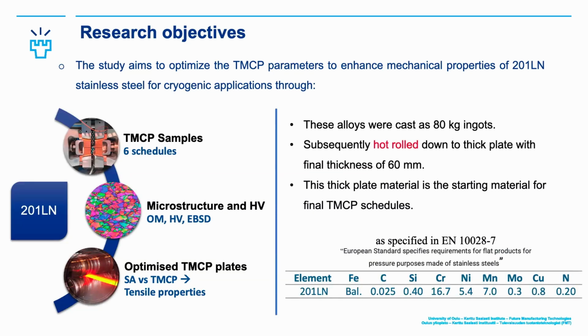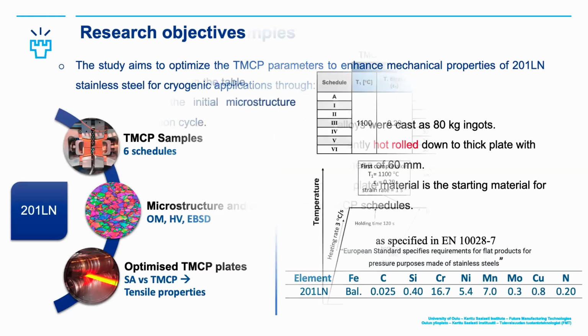Initially, we produced 80 kilogram ingots, then subsequently hot rolled with roughing, reaching a thickness of 60 millimeters. This thick plate material is the starting material for all the TMCP samples, and of course, after that, the TMCP plates. As specified in the EN standard, this is the actual composition of the 201LN used, and here we could find the manganese content is almost at the higher limit for this 201LN.